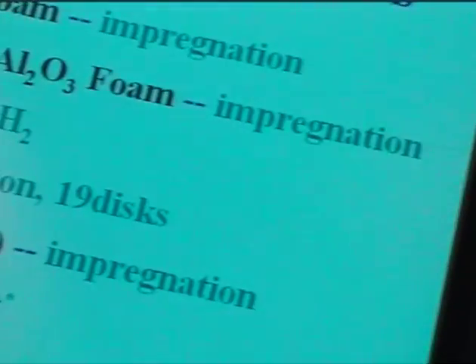We've got partially stabilized zirconia. There was a lot of good press about this being a preferred support for rhodium. So we thought, okay, well, we should investigate that as a support, which we did, either as an impregnation or a wash coat. And then we already talked about this reticulated foam. And then the honeycomb, that's cordierite that you could get for catalytic converters. Very economically viable. It's good for heat shock. You can cycle up and down in temperature and have good integrity.